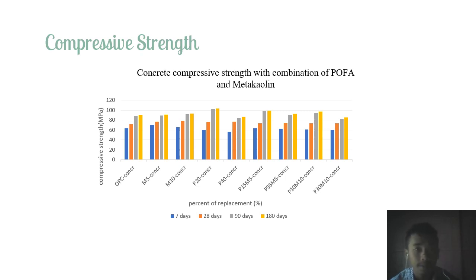For OPC, the compressive strength at 180 days was 90 MPa, and was 14.44% slightly higher than the control specimen for P20. The compressive strength decreased when POFA was added to 40% without metakaolin. Increasing the percentage of metakaolin from 5% to 10% combined with 10% of POFA caused an increase in compressive strength. This increase is due to the equal physical and chemical properties of POFA and metakaolin material.